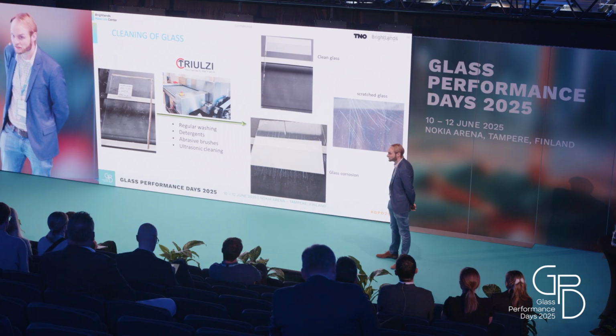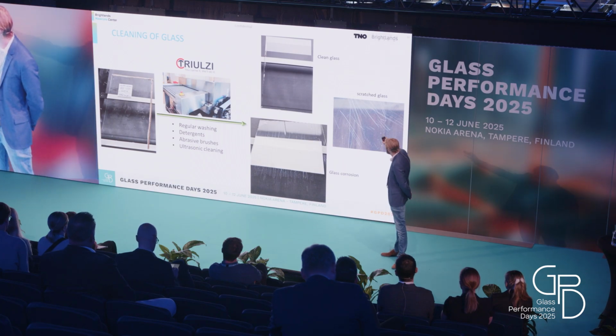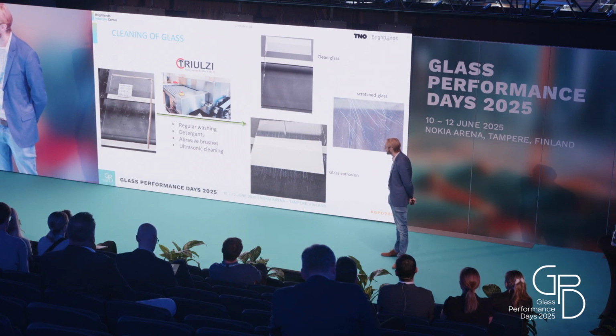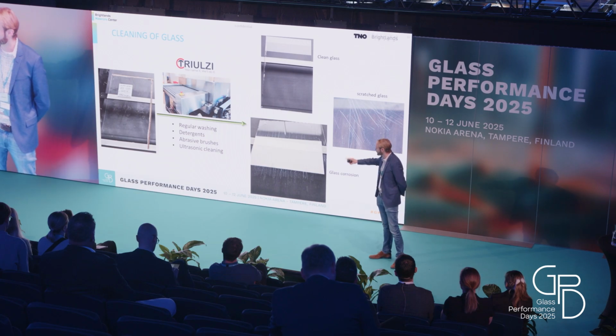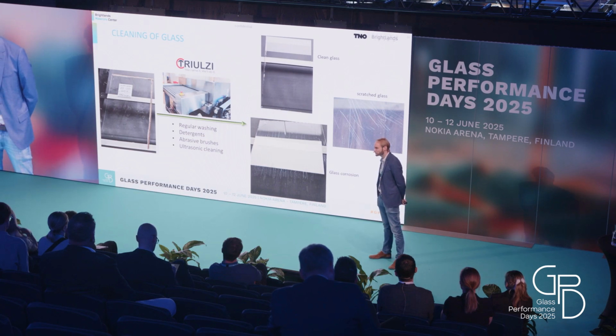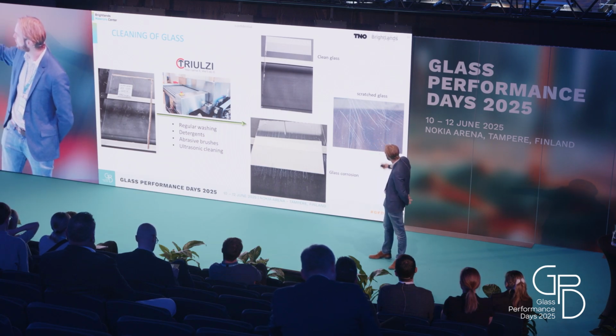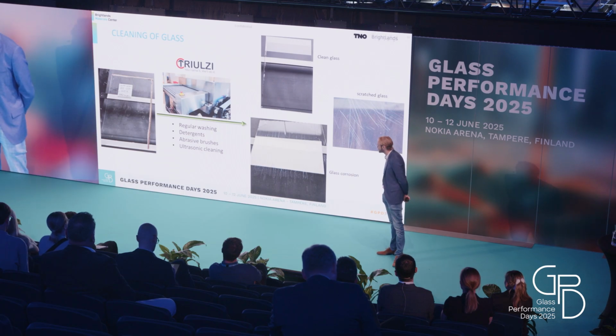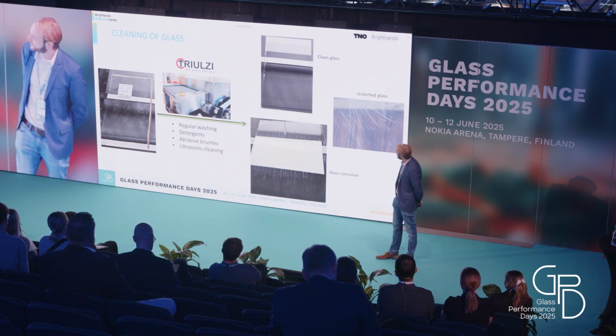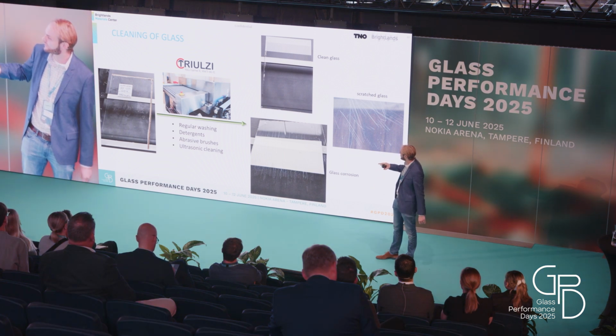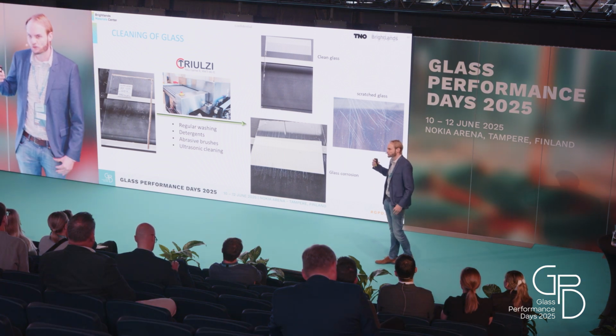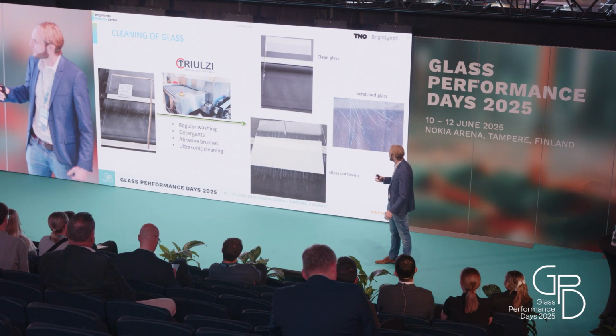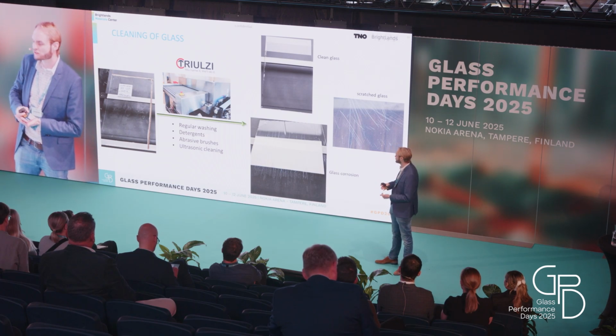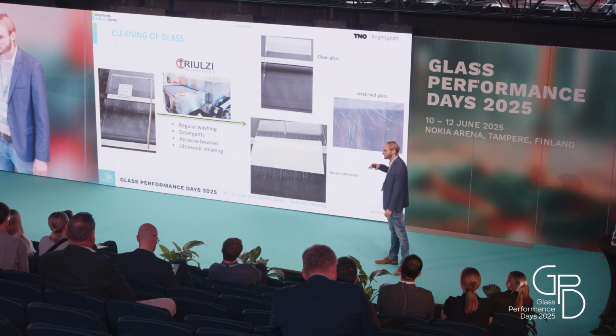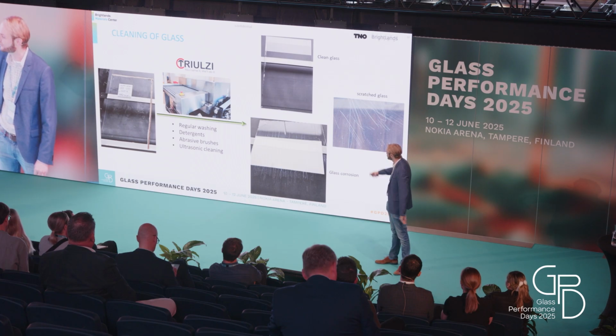Not all the glass is clean, not everything you can remove. Especially scratches are difficult to remove. There are possibilities with polishing via abrasive brushes to get rid of some small scratches, but deeper scratches you cannot get rid of. And what we also saw, especially for the outer glass pane, is glass corrosion. So here are also things where you can think about next strategies in a design for recycling concept: can I develop some coatings, for example, which prevent these kinds of scratches and glass corrosion happening in the future to make glass more recyclable?